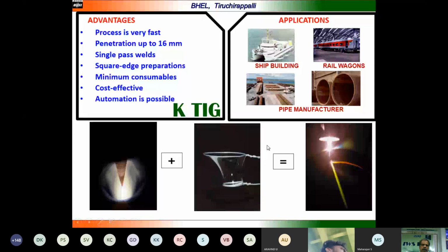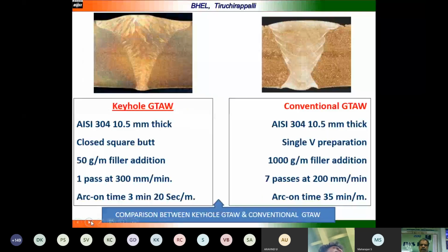And when we compare a keyhole GTAW and a conventional GTAW for stainless steel of 10.5 mm thickness, 304 stainless steel, there is a closed square butt joint without any root gap, against a single V edge preparation with root gap.